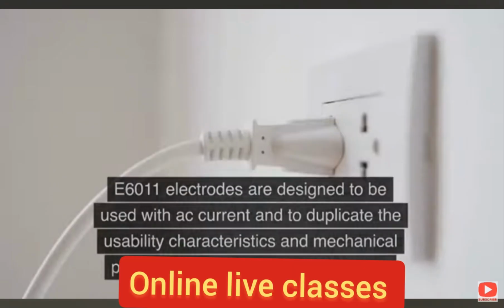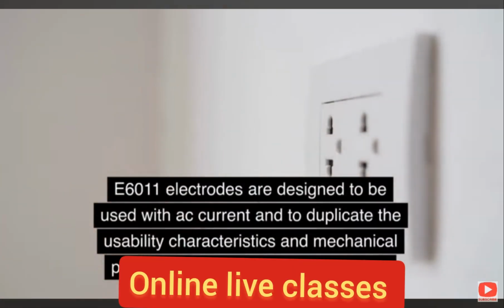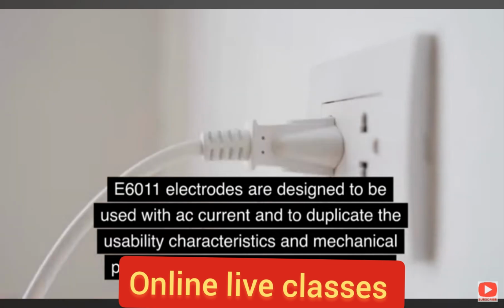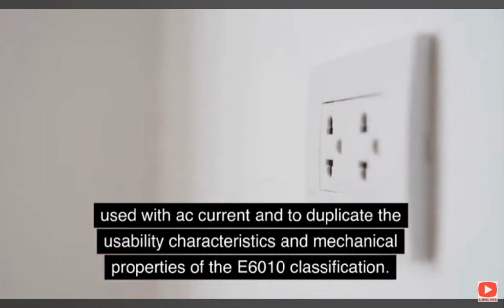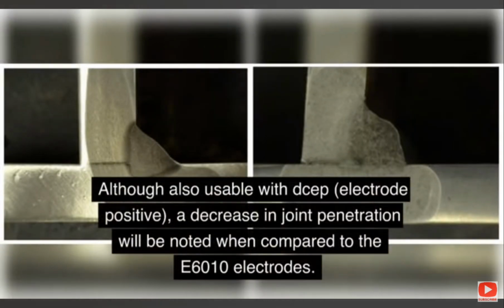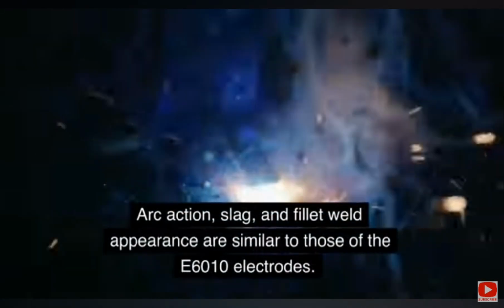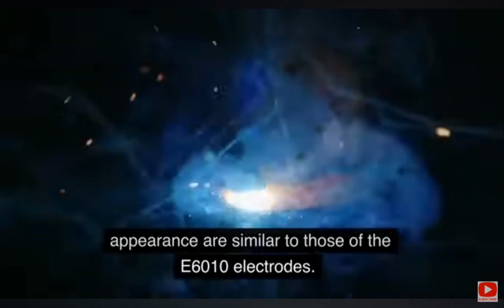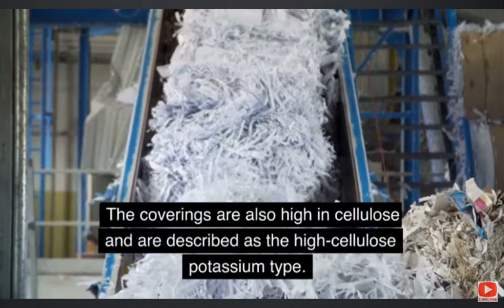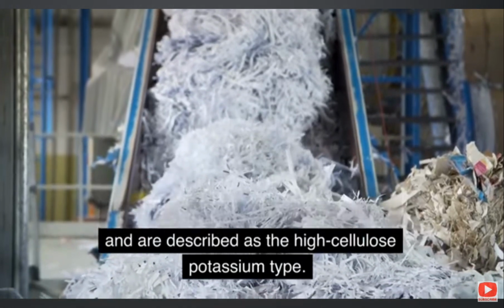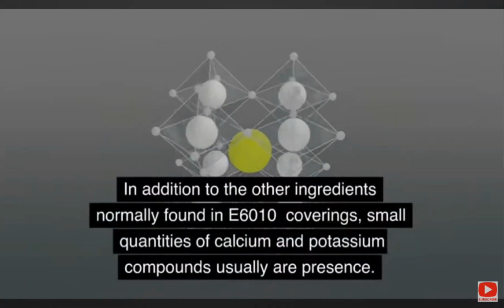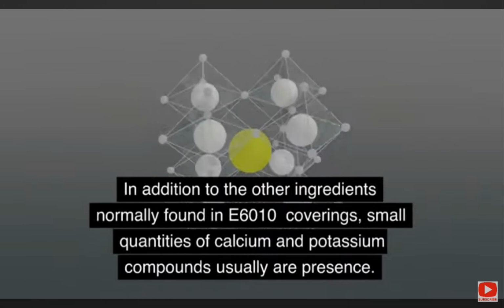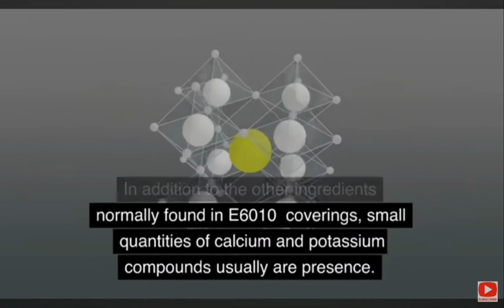E6011 welding rod. E6011 electrodes are designed to be used with AC current and to duplicate the usability characteristics and mechanical properties of the E6010 classification. Although also usable with DCEP, electrode positive, a decrease in joint penetration will be noted when compared to the E6010 electrodes. Arc action, slag, and fillet weld appearance are similar to those of the E6010 electrodes. The coverings are also high in cellulose and are described as the high cellulose potassium type. In addition to the other ingredients normally found in E6010 coverings, small quantities of calcium and potassium compounds usually are